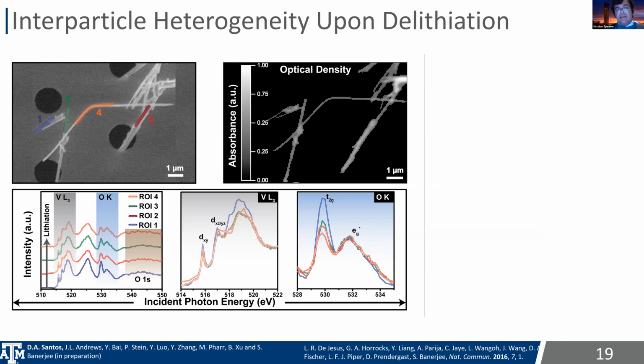Okay, so what are the consequences of small polaron formation, and then these diffusion limitations? One of the consequences is that different particles in an ensemble here, for example, particles 1, 2, 3, 4, are lithiated to different extents. Okay, and so this turns out to be quite important. We've spent a lot of time looking at this, and I've talked about this at previous TMS meetings.